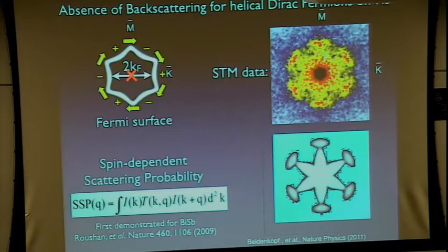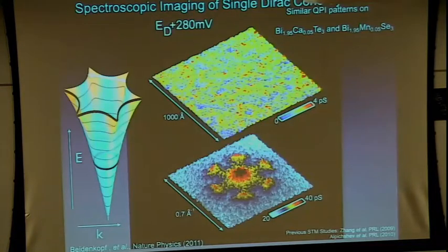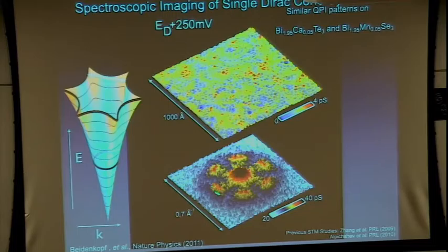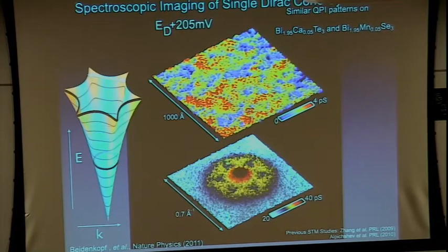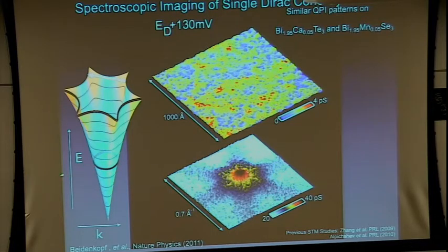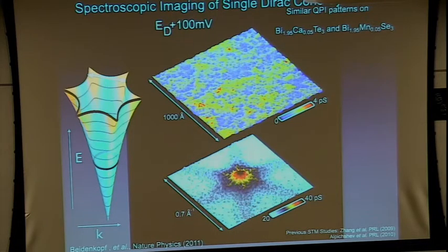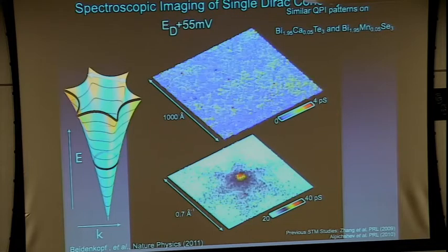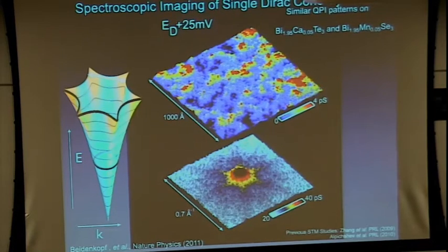In fact, look at this. So this is the scattering pattern. It's very well defined. It gives this nice circle. But now I go into the Dirac cone. Here, backscattering is also forbidden. But you see signal, because you can just go a little bit off, and that's allowed. In fact, unfortunately, in these papers, they didn't have enough signal to noise to see that. So they just thought, oh, it just disappears when you go into the circle region. It doesn't. All right. Good question.